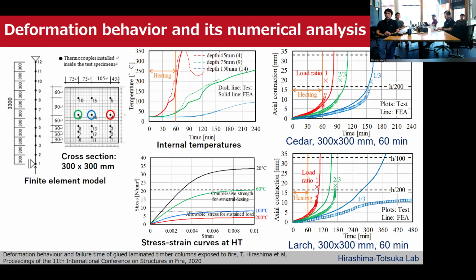The compressive deformation obtained by FE analysis, this line data, approximately agrees with the test results, regardless of the load ratio. If the mechanical properties of wood at high temperatures and the internal temperature during a fire can be properly determined, it will be possible to predict the failure time of mass timber columns.